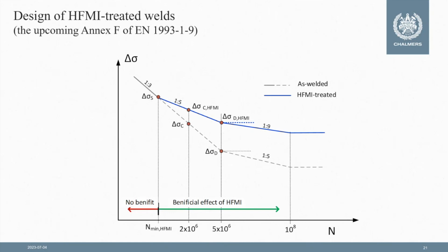So to start with, we look simply at the SN curve. The dotted line here shows the SN curve for the as-welded detail. As familiar for everyone, we have a bilinear SN curve with two slopes, 1 to 3 and 1 to 5. And what we achieve by doing HFMI treatment is partly increasing the detail category or the fatigue strength from delta sigma C to delta sigma C HFMI, which is higher. And the second thing we are doing, of course, is that we are changing the slope of the SN curve. So instead of 1 to 3 and 1 to 5, we have a slope of 1 to 5 and 1 to 9. And that adds, at least in the large number of cycle regime, an additional value from this HFMI treatment. There is a new point or a knee point introduced, which is called delta sigma S.